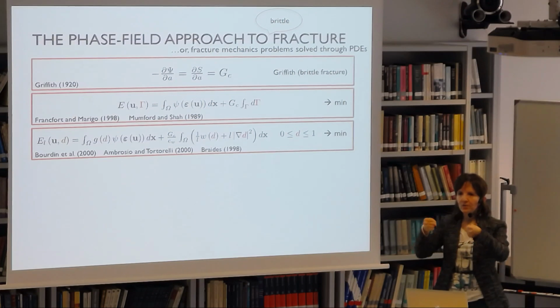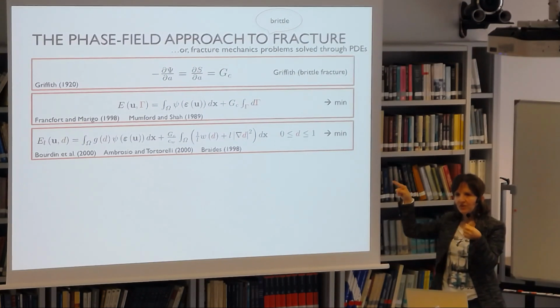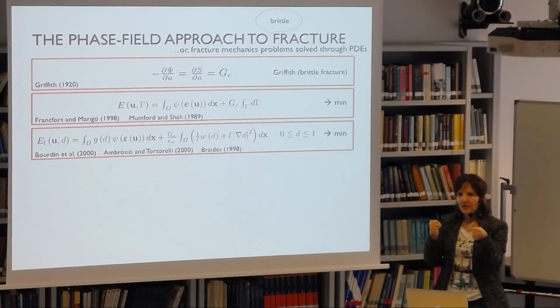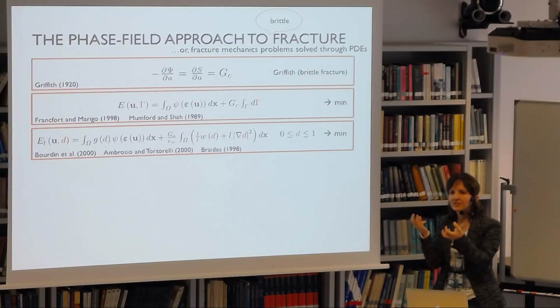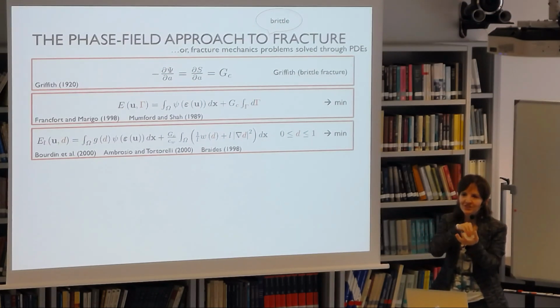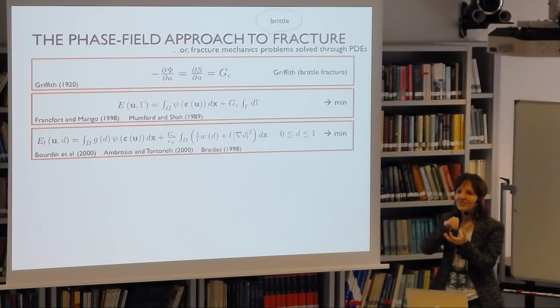So imagine you have a bar in 1D. You can write the differential equation of the phase field in 1D, and you can find the so-called homogeneous solution, where you neglect the gradient and you assume that everything is homogeneous. And you can find a relationship between tensile strength, length scale, elastic modulus, and fracture toughness. And so this gives you a consistent choice of L for cases where you don't have an initial crack, so for cases where you don't have an initial singularity, you can capture nucleation by an appropriate choice of L at a stress that you can control.